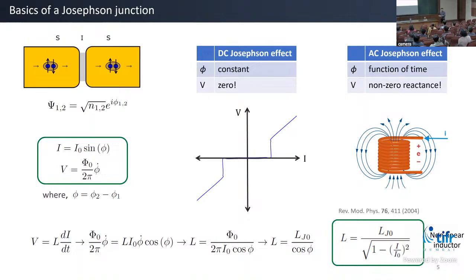The length scales are also quite different. For tunneling to occur, the thickness of the insulator has to be about 10 angstrom. Here it is about 300 nanometers, so 3000 angstrom. So tunneling is just not possible.